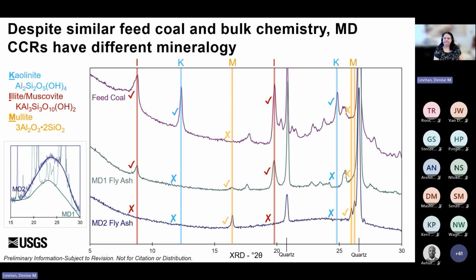So then looking at illite muscovite, which are sheet silicates or mica minerals represented in red with the I, you can see clearly here in the feed coal, big peaks, smaller peaks, but definitely still present in the MD1 fly ashes, but then gone, no peaks in the MD2 fly ash. And similar to kaolinite, illite or muscovite starts to thermally break down around 800 to 1,000 degrees Celsius. So you see it present in the unaltered or unheated coal, present in the less heated fly ash, but then not present in the more heated fly ash from the PCF boiler.